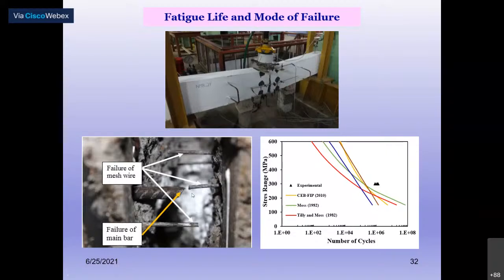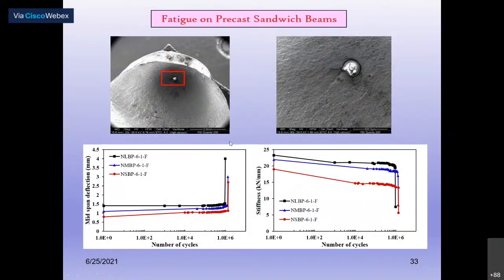When you take the cyclic loading, this is the type of failure. The bars snapped like this, a clear failure of the rebars under fatigue loading. Again, it comes down to the manufacturing difference in the reinforcement bars. When the stress levels are low, it's fine. But when there is a manufacturing defect like this, as I mentioned, stress concentration led to the initiation of microcracking.